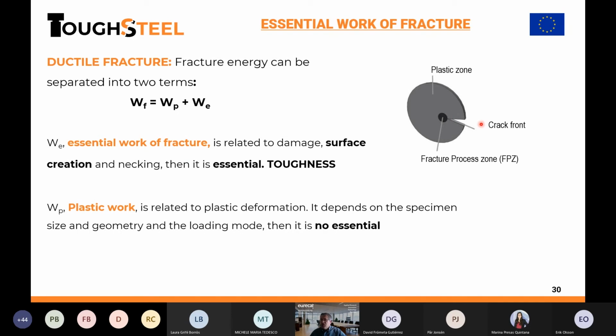But in ductile materials, in front of the crack, we have a fracture process zone where all the cracking takes place, and it's surrounded by a big plastic zone that also depends on geometry. So if we want to understand what happens just in front of the crack tip, we have to be able to separate the plastic work and the fracture work. So we can say that the total work of fracture can be divided into the plastic work and the fracture work. We call it essential work because this is related to damage.